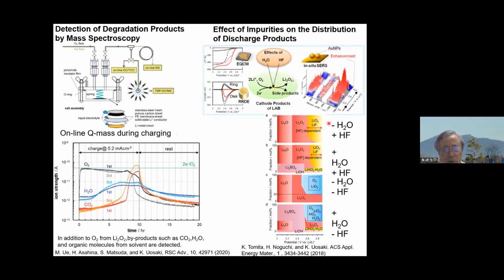And also we found that the products very much depend on the potential and also the impurity in the solution. Often people say the water content in the solution in the battery is 50 ppm or something. It's quite good, they say, but if you convert it to molar, it's a kind of millimolar, which is very high in the electrochemical sense.